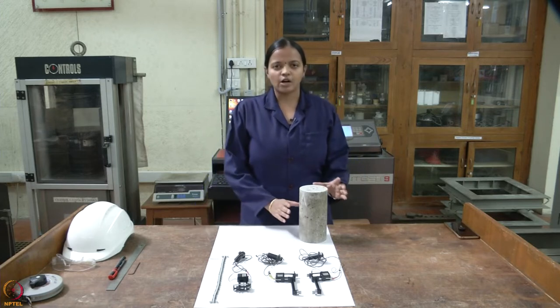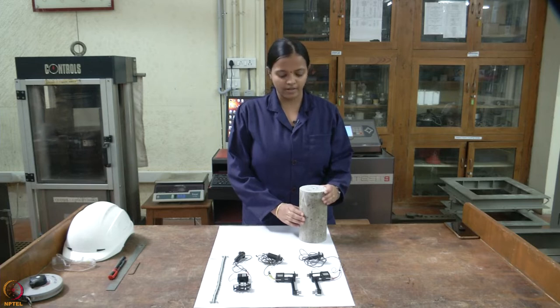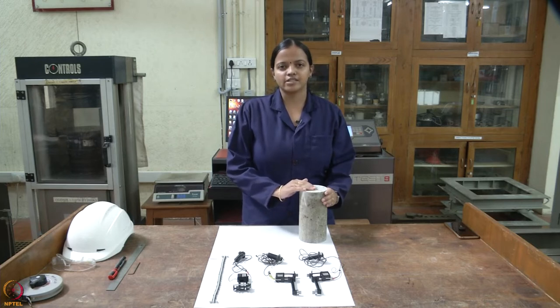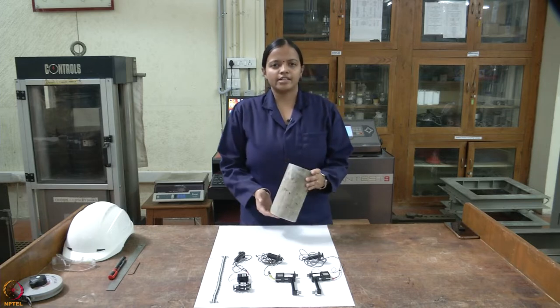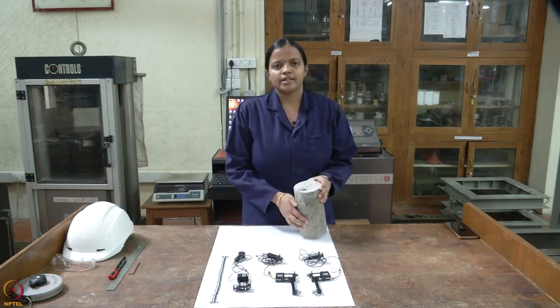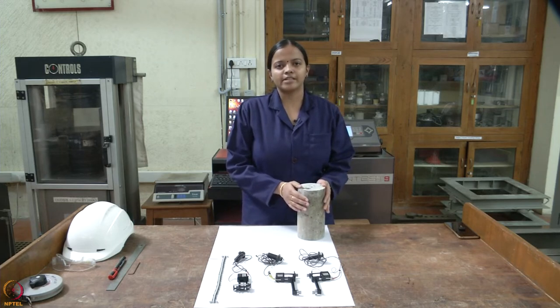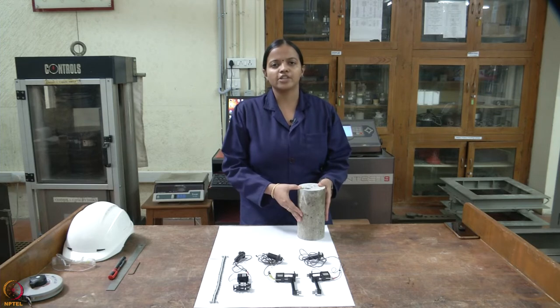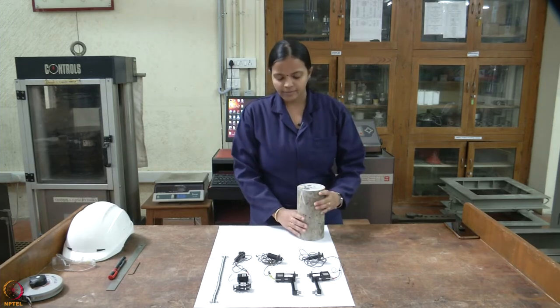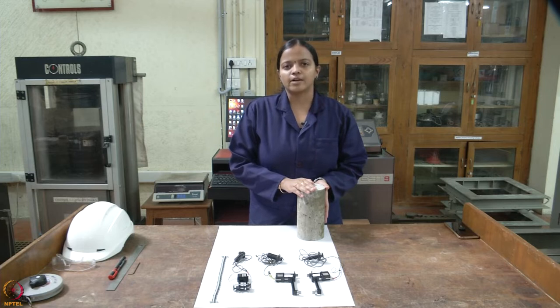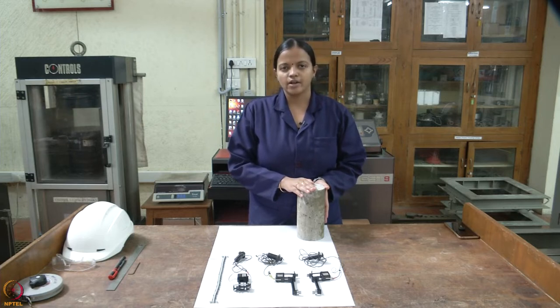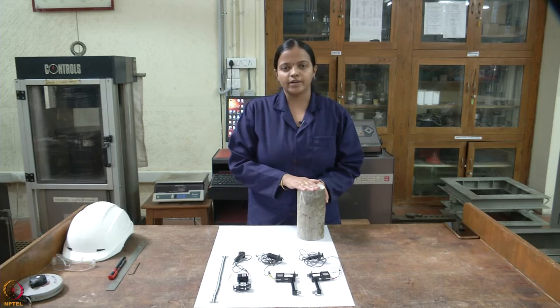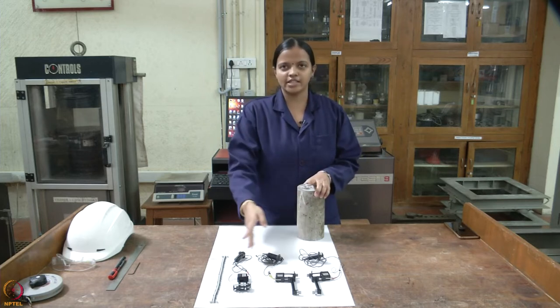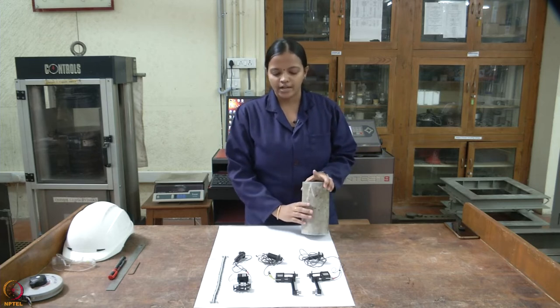Today I will be showing how the testing of compression is done in the closed loop testing machine. Here we will be getting the complete stress strain curve of concrete under compression. So we need a cylindrical specimen for this, and the dimension of the specimen should be maintained in such a way that the height to diameter ratio is always less than 2. And the testing is mainly controlled by means of circumferential strain control in order to maintain stability during the testing process. So these are the accessories required to do the testing.